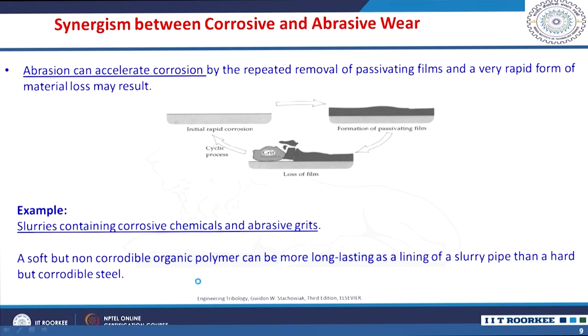So, the material removal in such corrosive and abrasive wear stress conditions is because of the synergetic effect of corrosive and abrasive wear. You see here, initially you will have rapid corrosion. So, you will have a film, and when a hard grit or hard asperity comes in contact, this film will be broken, and then again the cyclic process proceeds with corrosion, but now at a very rapid rate. Then again the material forms a passive film, and again the material is removed. So, it is a continuous process.